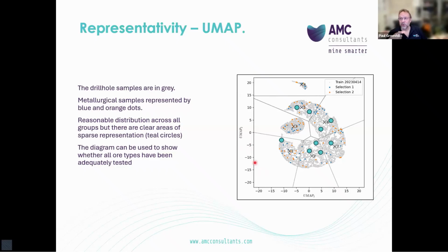And as we've seen previously with the sulfide projection, we could also plot, for example, if this is a porphyry, we could plot copper, we could plot gold, we could plot iron. And that allows us to determine whether or not we've actually got reasonable coverage for those elements within this metallurgical selection set. The other thing that we've represented on this diagram is areas where there are, in fact, sparse selection. And that gives us an opportunity to add additional metallurgical samples to the group to try to cover those areas where there is limited representation.